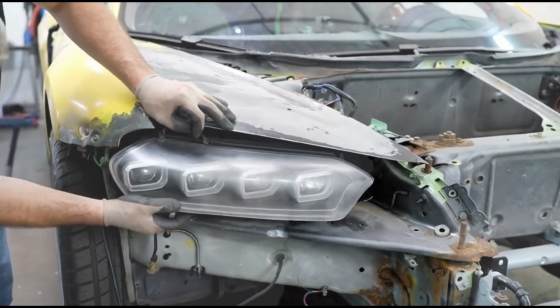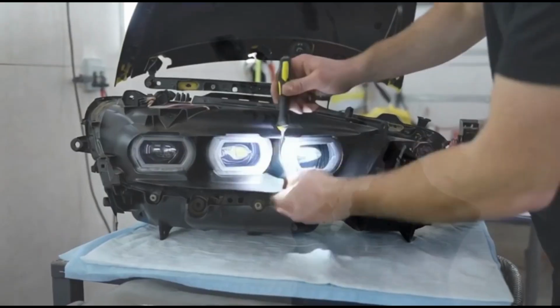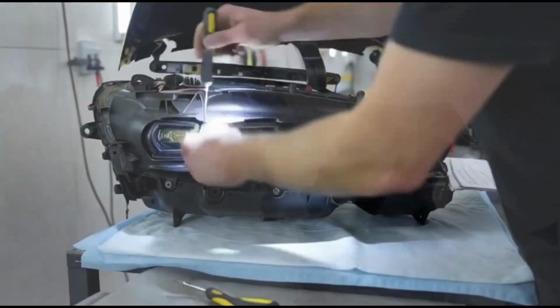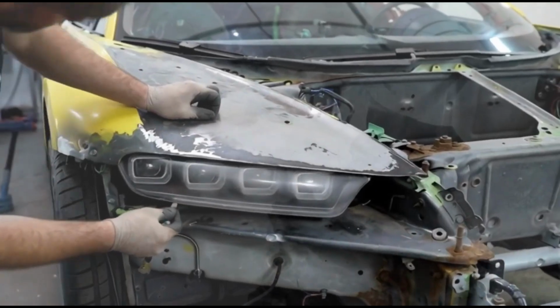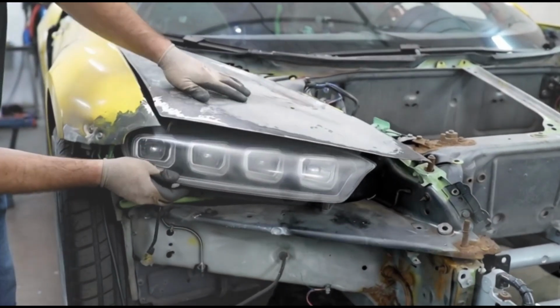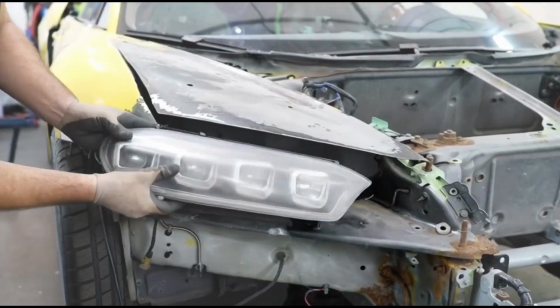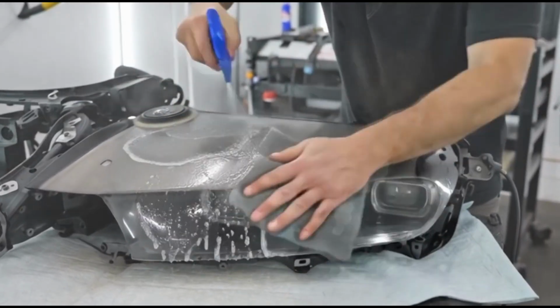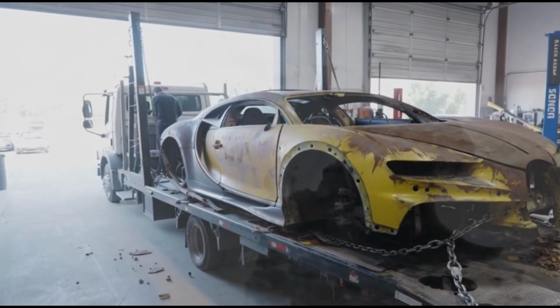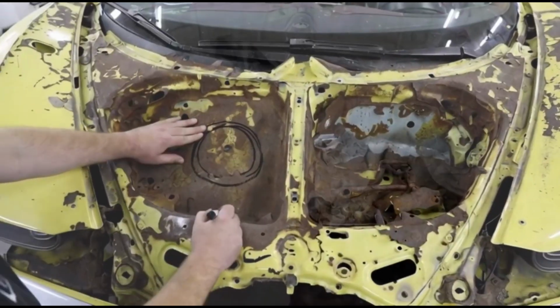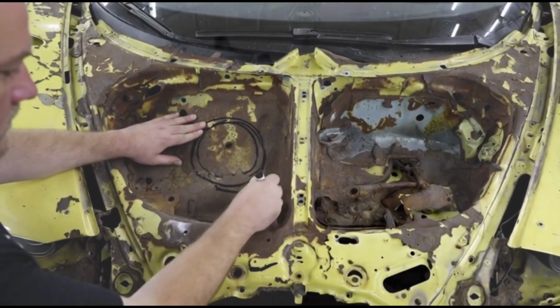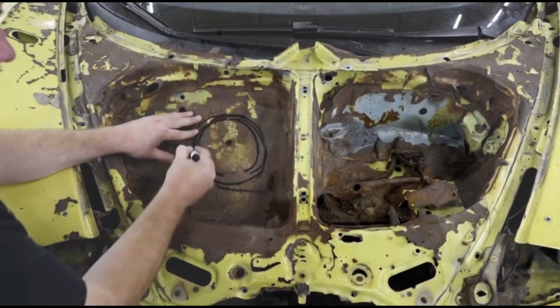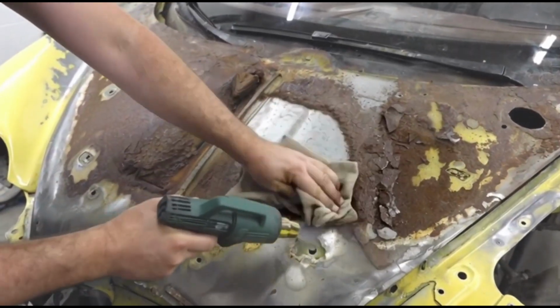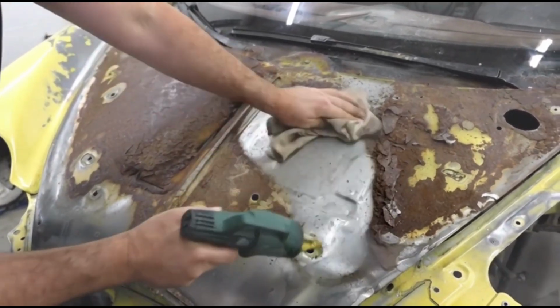The phosphating process doesn't remove the rust, it converts it. Every molecule of iron oxide on the surface becomes iron phosphate. The treatment penetrates into the rust layer rather than sitting on top of it, converting the problem into the solution at a molecular level. The resulting iron phosphate layer serves two purposes simultaneously. It eliminates the existing rust by transforming it into a stable compound, and it creates a surface that is significantly more resistant to future oxidation than bare metal, because the phosphate layer itself acts as a barrier against the oxygen and moisture that cause rust to form.